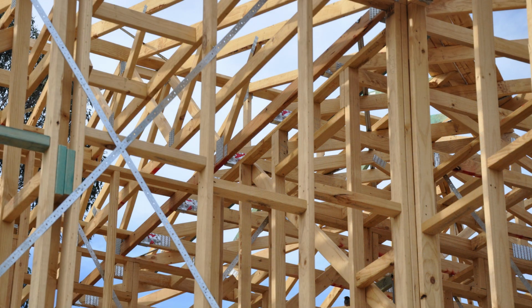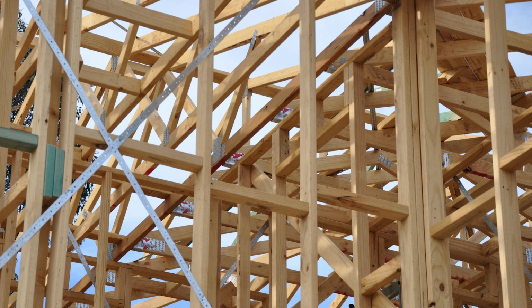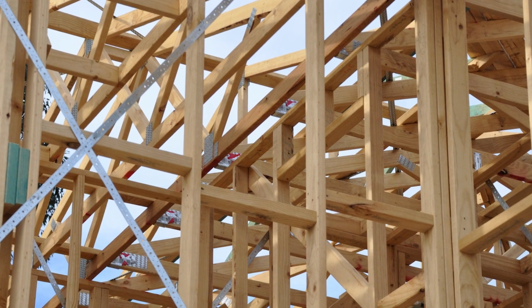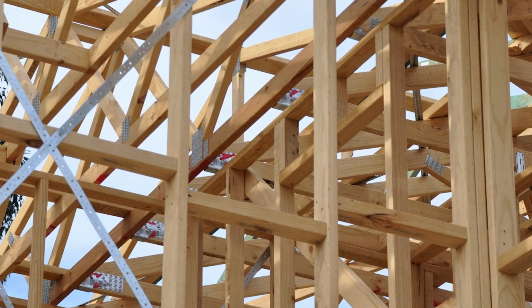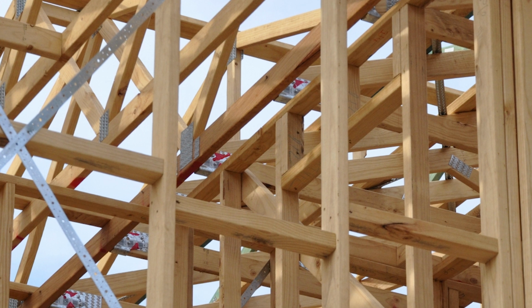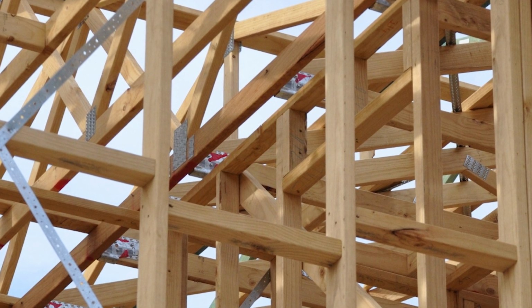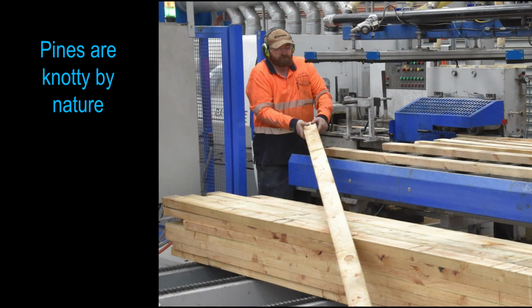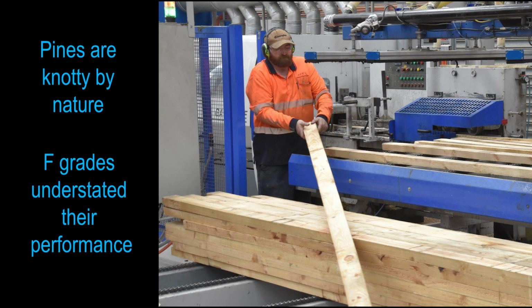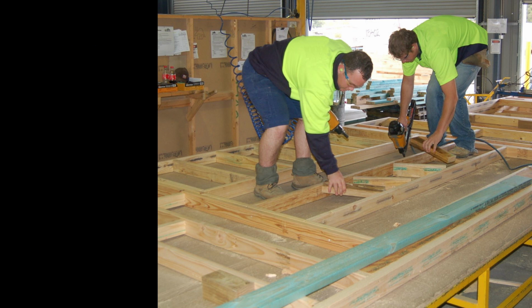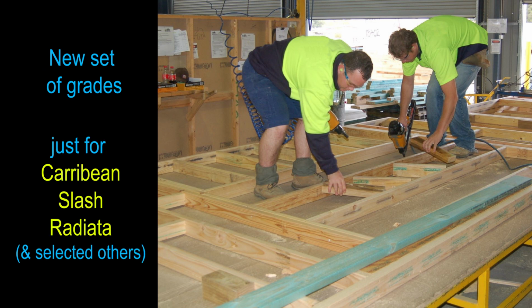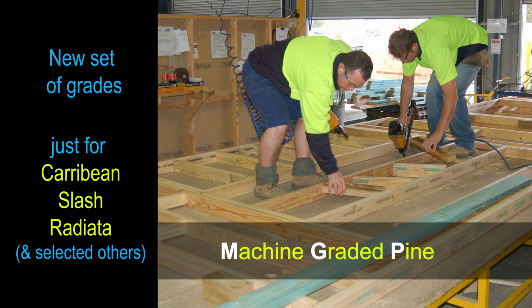But over the years, it was found that F-grades weren't always accurate in predicting how the plantation pines would perform in a structure. These species include radiata, slash, and Caribbean pine. Pines are knotty by nature, and the F-grading system was tending to understate their performance in actual wall frames and roof trusses. So a new set of grades was developed just for this particular group of pines, called MGP.